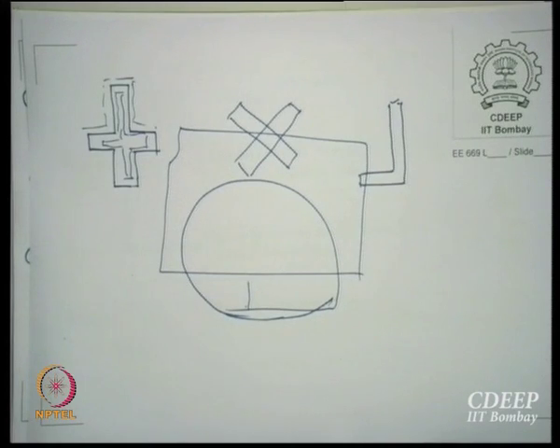Now the problem starts. In most cases the kind of lithography I do is called contact printing. After this alignment is done, with the mask perhaps 25 microns away, I bring it down and allow the mask to touch the wafer. The emulsion side is below, which means there is no gap between the mask and the initial pattern in the resist. Now there is a problem there itself, because in any XYZ system it is mechanical, there are always backlashes, or what are called inertial motions.